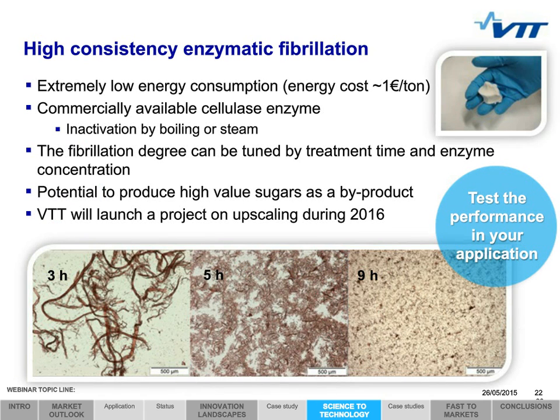The benefits of HefCel fibrillation technology include the very low energy consumption, which we have calculated to be around €1 per ton. The method can produce CNF materials with variable fibrillation degree, as this can be tuned by the treatment time and enzyme concentration. In the optical microscope images shown at the bottom of this slide, you can see how the size of the cellulose fibrils is reduced with prolonged treatment time, when moving from 3 hours to 5 hours and 5 to 9 hours.